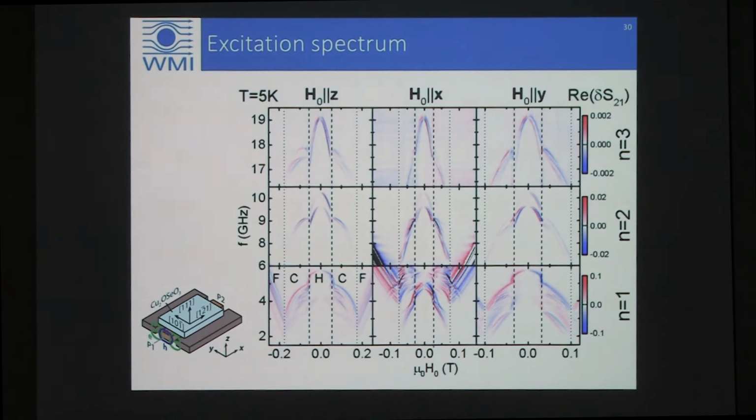Right, but it's definitely a multi-Q state, right? You can also see that in the helical, right? There's these 2 sets of resonances which are very clearly separated, which we think is the multi-Q, because you're basically seeing one which is dominantly out of plane, giving you I think the low resonance frequency, and then the in-plane ones are rather degenerate because it's almost like a thin film, right? So you see these 2 different resonances. You have domains. It's called the multi-Q state, right? Where you have in the helical phase, the external magnetic field is just not large enough to saturate it to the conical phase to pull the pitch vector along the field, right?